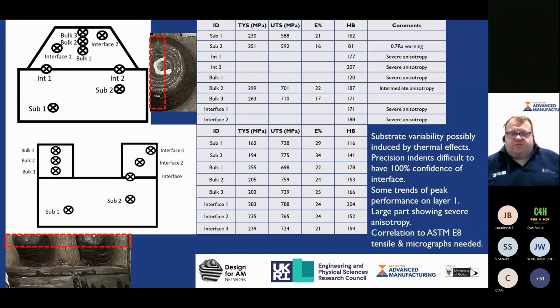Performance was quite good, I would say, quite consistent in many areas with what we would expect to have seen from the laser powder bed. So there was nothing too alarming, but there was quite a lot of variability in hardness. Again, there was always a chance that that's down to the coupon itself, maybe a heat affected zone from WEDM wasn't quite removed. Certainly some additional work to be done. We only managed to get the data fully completed just yesterday, so this is one to be continued into January as we do a little more exploration in that field.